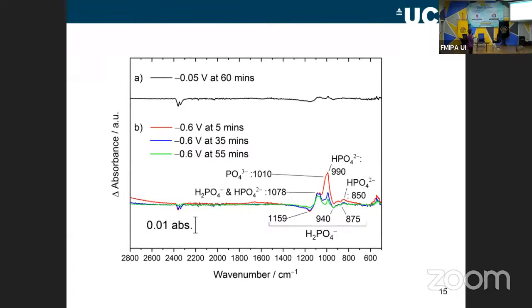So the type of spectra we record are called difference spectra. And they're difference spectra because we're measuring changes in absorbance as a function of the wave number. So what we do is we take a spectrum under conditions where no potential is applied. Then we will take another spectrum where the potential is applied, and what we're showing here is the difference between the two. So it's changes from no potential to potential being applied.